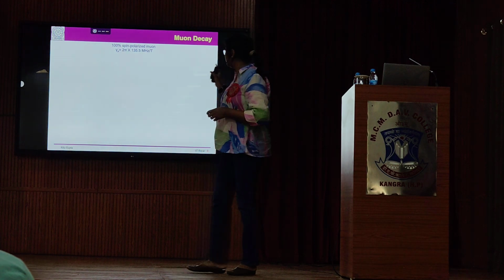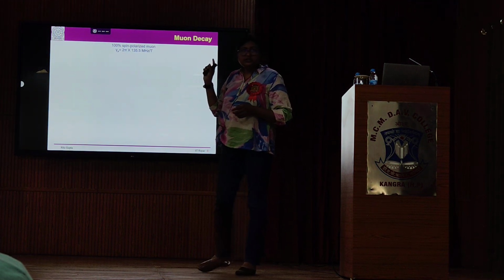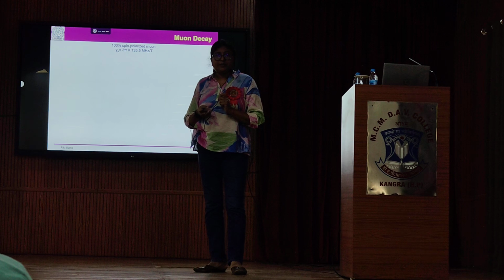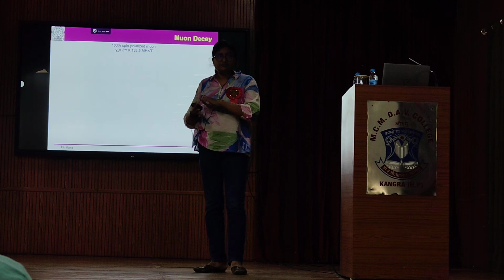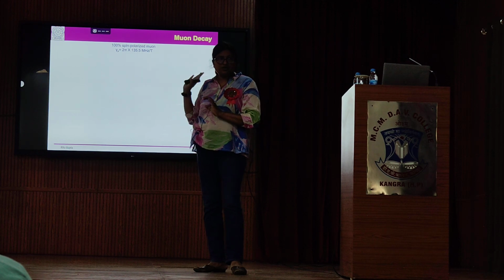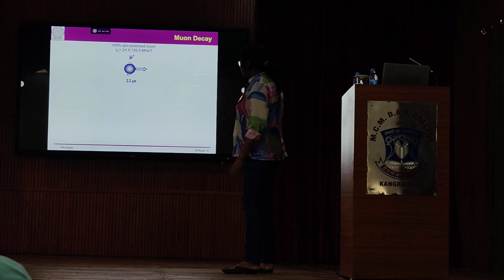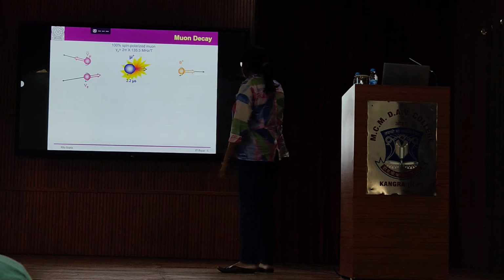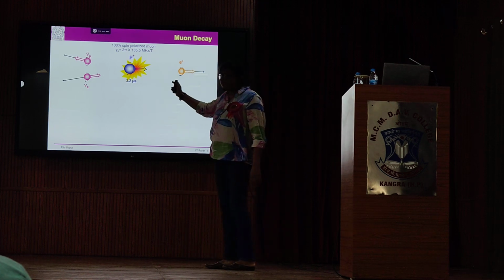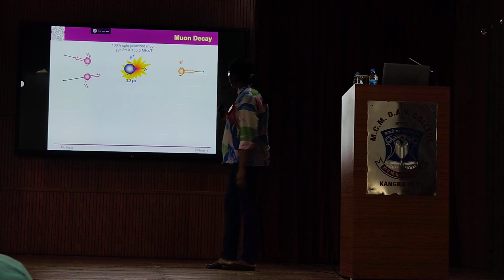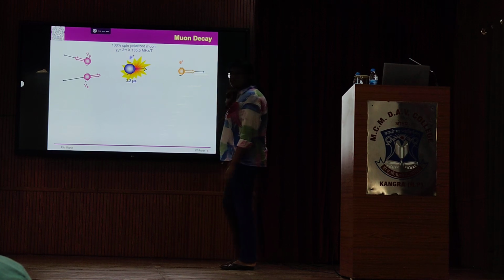Okay. So why muon? Because if you look at the gyromagnetic ratio of the muon, it is quite high. If there is a quite high gyromagnetic ratio, that means you can probe even a tiny magnetic field of any material. Okay. So if there is a vortex state in a superconductor, you can probe that vortex state using the muons. Okay. So what normally is a muon? The muon has a lifetime of 2.2 microseconds, and after that 2.2 microseconds, it decays into a positron, and then a neutrino and an antineutrino. Okay. And this is a three-body decay, so it is a kind of weak decay.